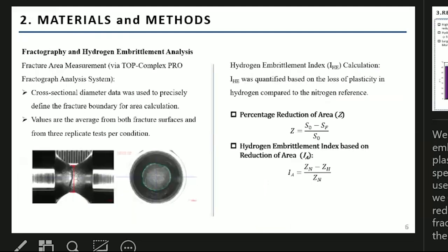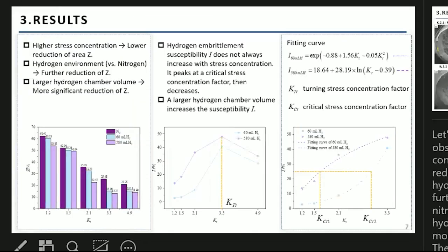And we calculated the hydrogen embrittlement index as a measure of plasticity loss. Given the notched specimen design and the inability to use an extensometer in the chamber, we represent the index by the loss of reduction of area. The corresponding fracture area was measured using an analysis system. Let's move to the results.